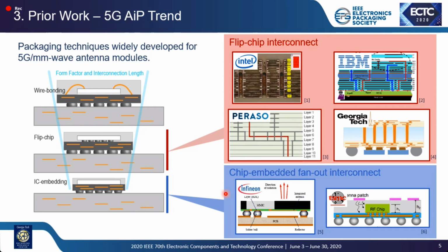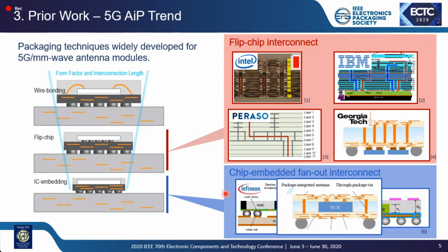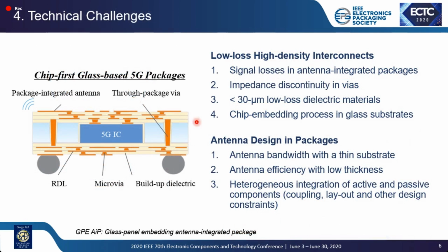Their packaging technique is technically based on an epoxy molding compound, which goes a bit against the form factor challenge. So our idea is to do this chip embedding or fan-out packaging with a glass substrate. With this glass panel embedding antenna integrated package, we have an IC embedded, with the antenna sitting on top, and redistribution layers for signal and power distribution on both sides of the package. This packaging structure addresses these technical challenges.